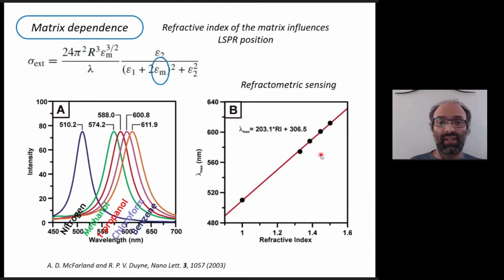Why? Well, because in refractometric sensing, this is really where it all comes from. Epsilon m is referred to the refractive index of your solvent, of your medium. So if you change this, you will automatically change the resonance condition of the plasmonic nanoparticles. And this is why we have this refractive index dependence. So as you can see here, this is a silver nanostructure in air or in different solvents. It's not very easy to read, but methanol, propanol, chloroform, and benzene. So with increasing refractive index, you have the peak that moves to the red, and you see that there's roughly a linear relation between the wavelength of the peak and the refractive index of the medium. So of course this can be very interesting, and I will show you in a few slides how this has been used and proposed.